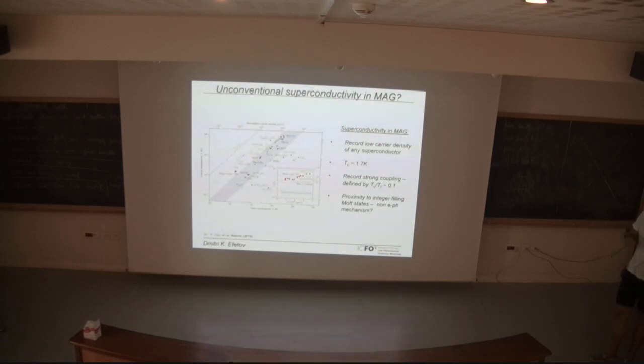So the Fermi temperature of any superconductor is basically the lowest in bilayer graphene. The carrier density is almost 3 orders of magnitude lower than, for example, in the cuprates. At the same time, Tc is not terribly low. Tc is 1.7 Kelvin. Again, it's quite low compared to the cuprates, which have Tcs up to 150 Kelvin. But comparing it to the Fermi temperature, this number is not so bad.